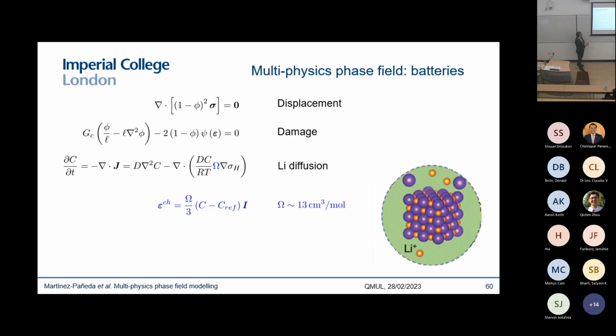One thing I want to say is that when you look at the equations, they're actually not very different from the hydrogen problem. Again, you're solving a coupled deformation, diffusion, damage problem, and there are essentially two differences. One is that our fracture energy does not depend too much on the lithium content. There are some mechanistic calculations by the group of Bill Curtin where they see some effect, but it's not very significant, nothing to do with hydrogen, where the effect is massive.